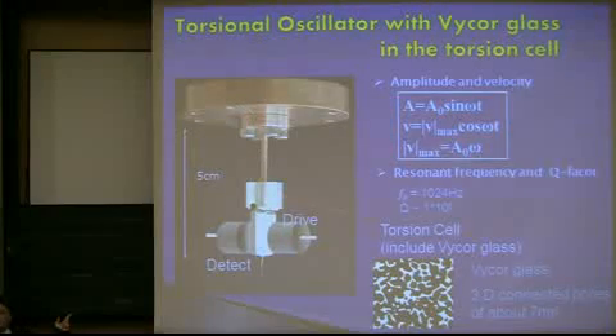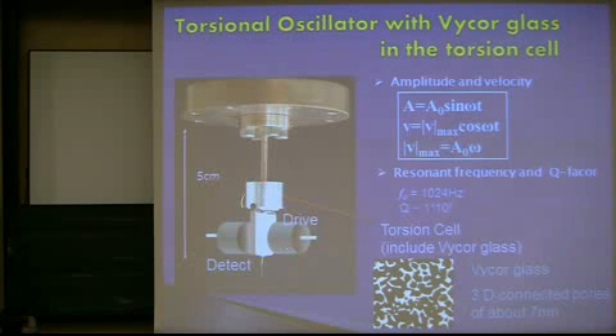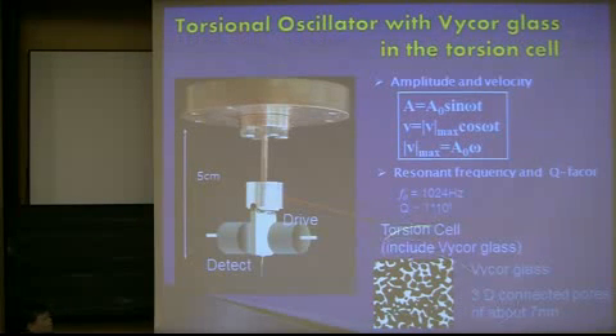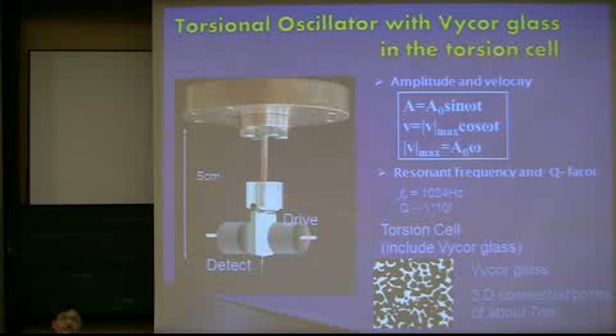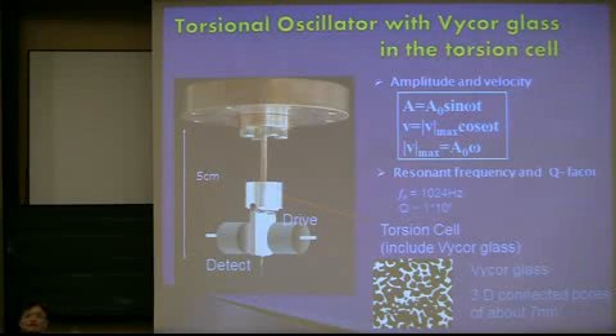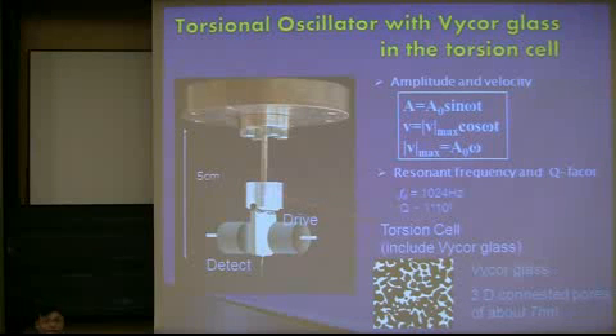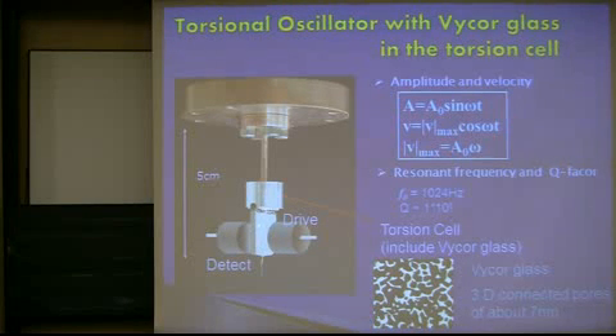And this is a real picture of the torsional oscillator that I used in the experiment. This torsion cell contains Vycor glass, and a typical pore diameter of this glass is only 7 nanometers. At the beginning, we used this porous glass because we know from the prediction that if you have defects or other dislocations, then you have a higher probability to find the supersolidity. Okay? That's why at the beginning, we used the porous glass in the cell. And here, this is the central electrode strongly attached to this torsion cell. This central electrode is coupled capacitively to the detection or drive electrode. This is like a simple parallel capacitor.